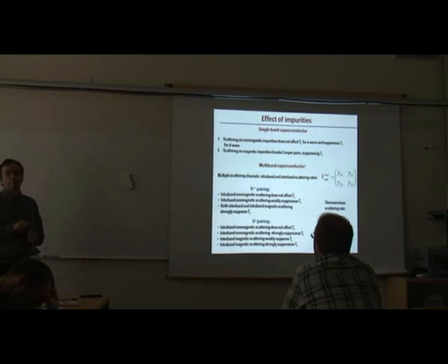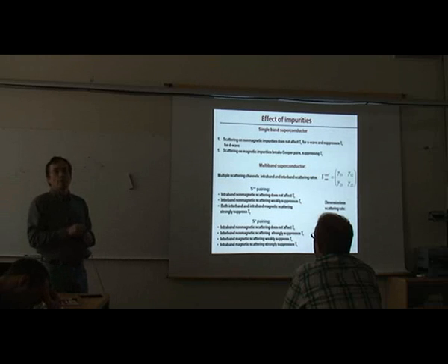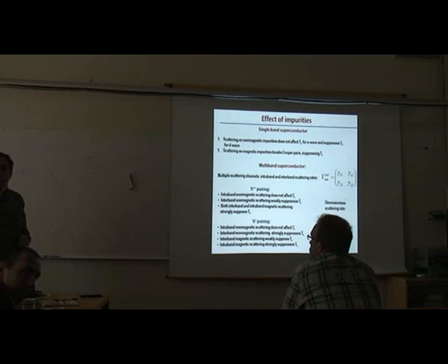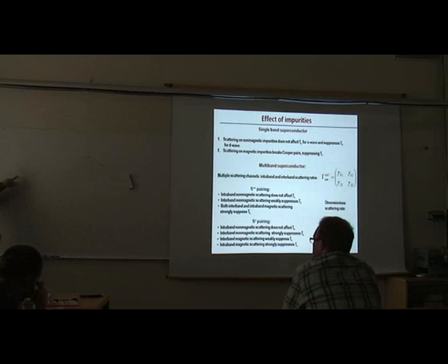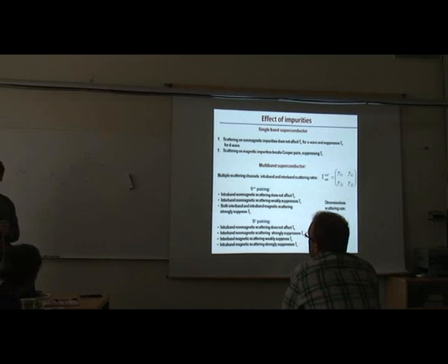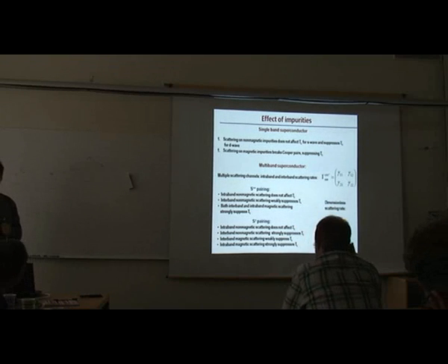But I don't see how you could possibly have the symmetry of the scattering in S plus minus. Okay, here you have S wave here and S wave here. Now, here the order parameter is positive, here it is negative. Now, I'm scattering from here to here, but what kind of impurity can do that? Any non-magnetic impurity. If the Fermi surfaces are the same, let's say assuming that they're just identical, but one has positive and one has negative order parameter, then the effect of non-magnetic impurities in this case is exactly the same as the effect of magnetic impurities in a single band superconductor. So they do suppress superconductivity.